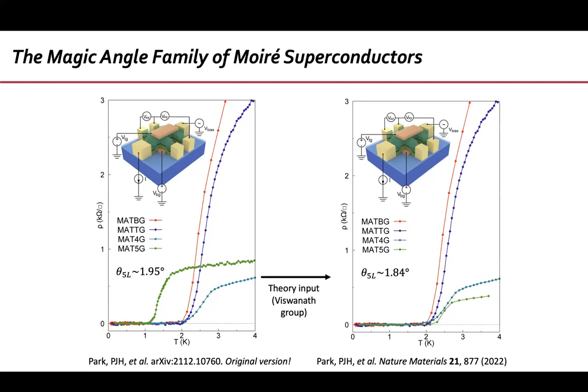So, yeah. How much is the sample to sample variation? Right, these are traces. Remember, we have displacement field, we have density. So these are entire regions. This is an optimal doping and an optimal displacement field for our best devices. There's a variation of devices depending on the two parameters. We have many devices. So I chose the best of each within the limited sample. Of course, because with the twist angle, if you get out of the twist angle range, the critical temperature is very, very small. So there's all kinds of variation.